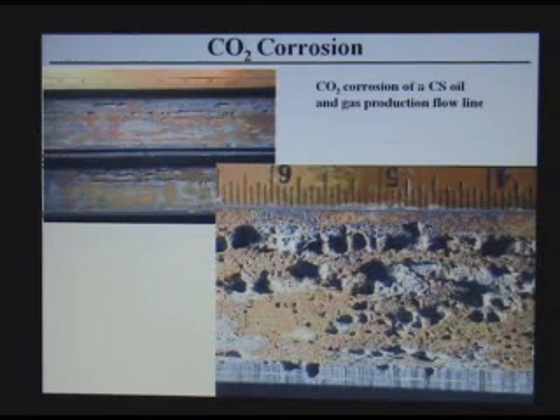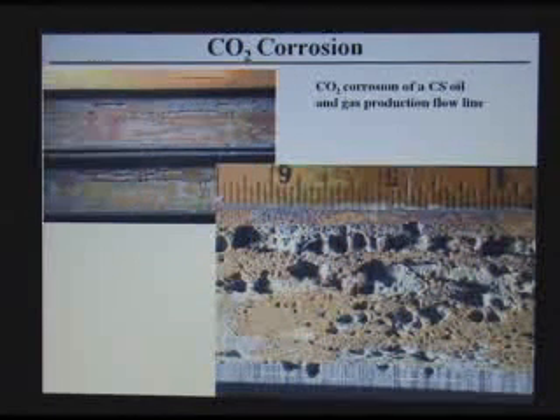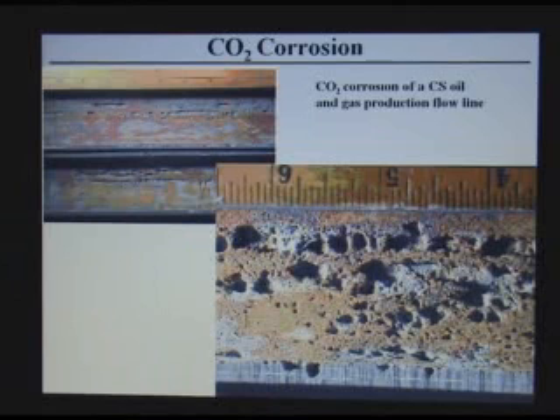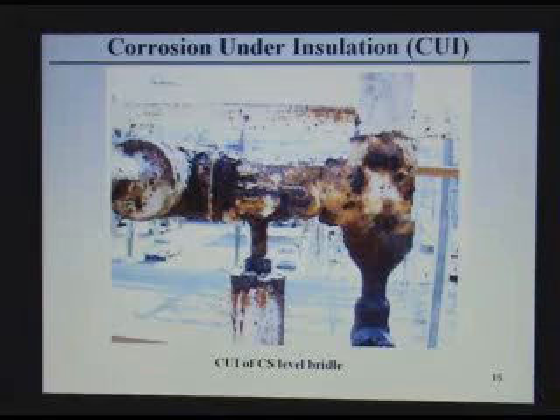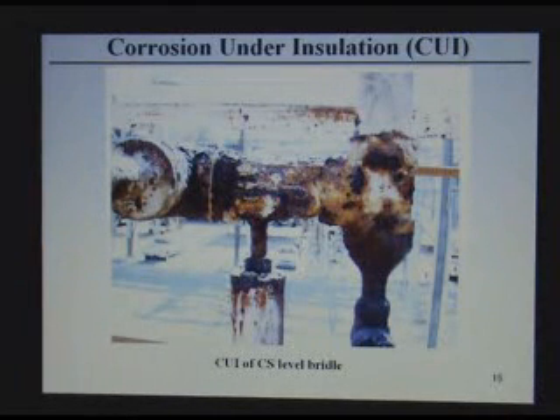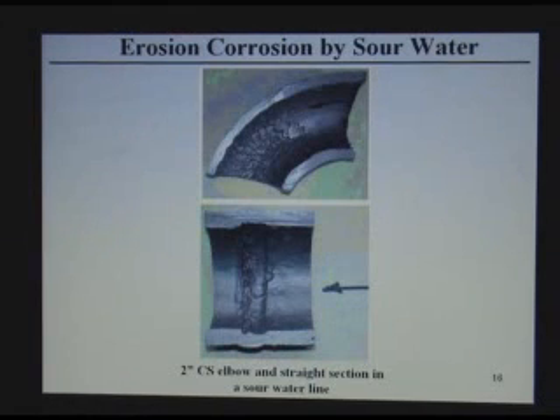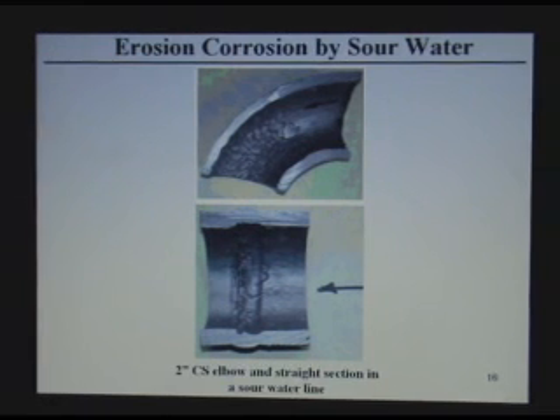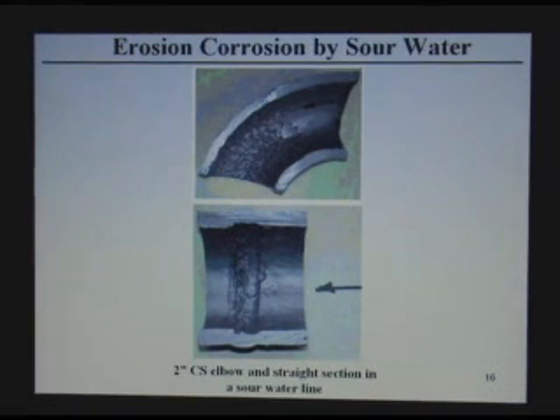And this is wet CO2 corrosion, where it is very characteristic. You have deep, sharp pitting, and this is what happens if you have wet CO2 corrosion. This is under insulation corrosion. And see what happened under the insulation. This is erosion corrosion, where you see the effect of flow, where the flow impinges on the metal, so it accelerates the corrosion, and that's why they call it erosion corrosion. If you have a weld, it is also like an obstruction in the flow, so it makes localized corrosion here.